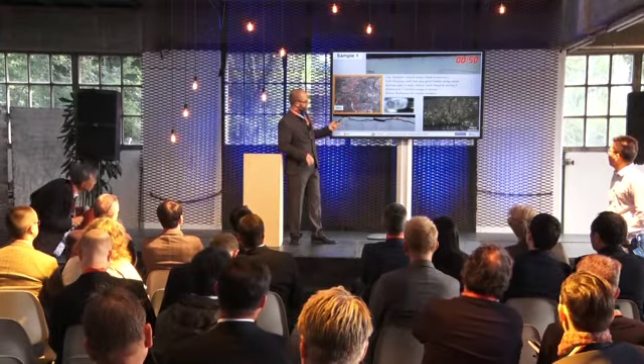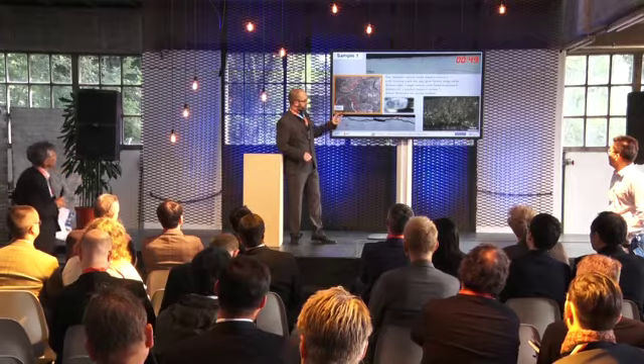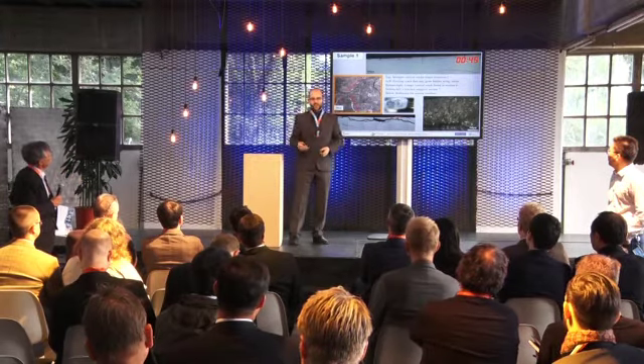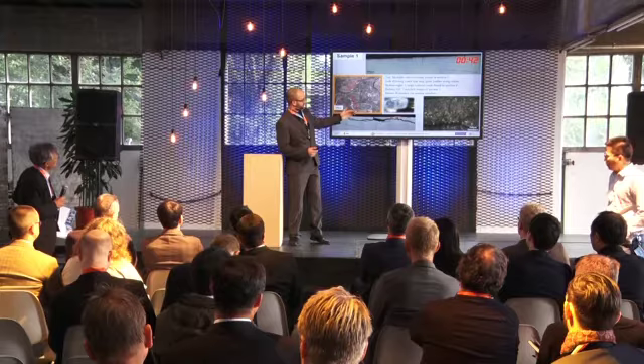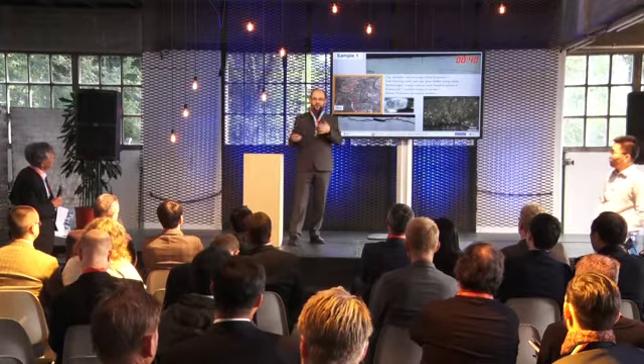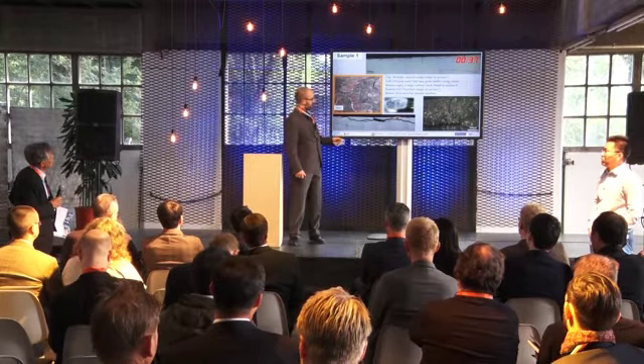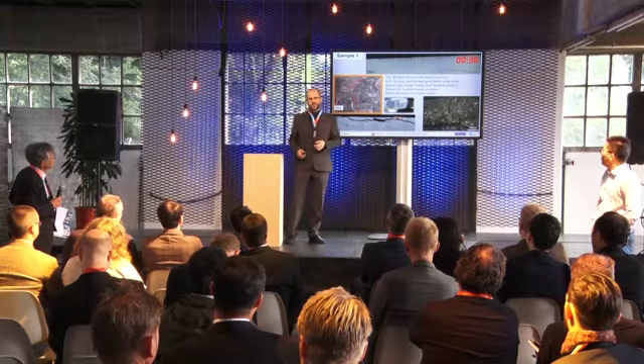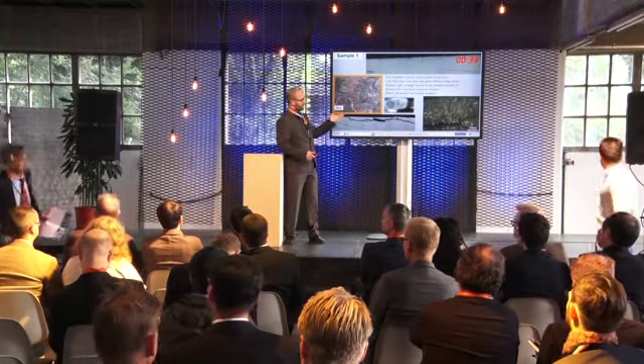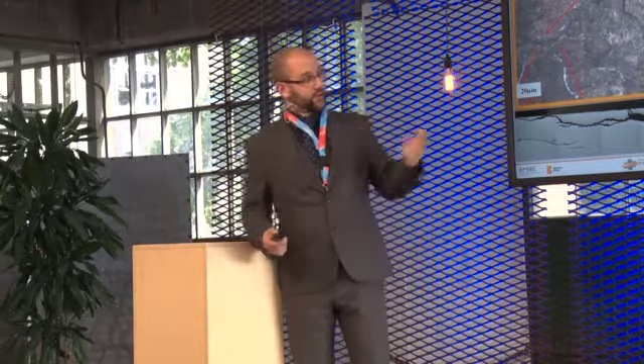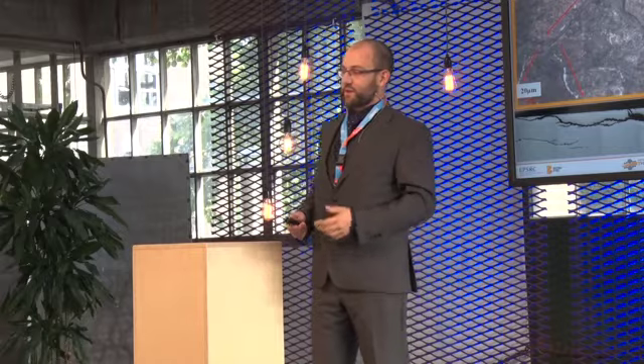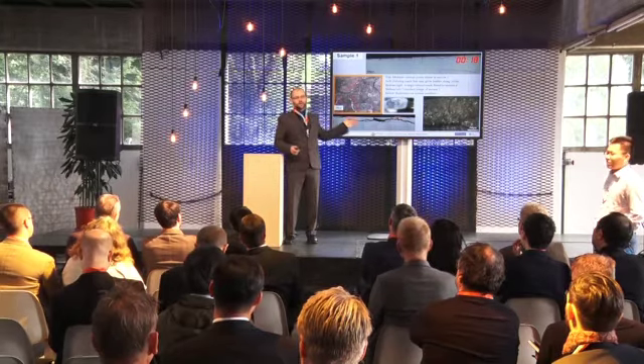Yes, this is something that I found in a couple of places. So there seem to be much straighter cracks, which are typically thermal damage, but then you have this saw-like effect due to cyclic loading on and off, which is much more mechanical. And I'm looking for microstructural sensitivities, and when it seems to be more thermally caused, it just seems to travel in very straight lines with no regard for the microstructure. But then there's also places where it will work its way around the grains and take the easier path, as squats typically do. So it's not simply that all these cracks are caused by thermal damage, there is mechanical load involved as well.